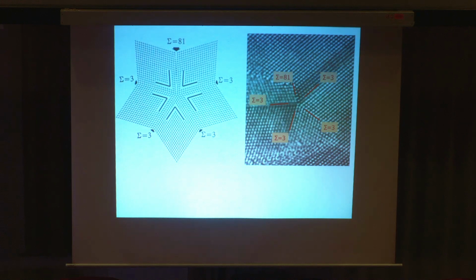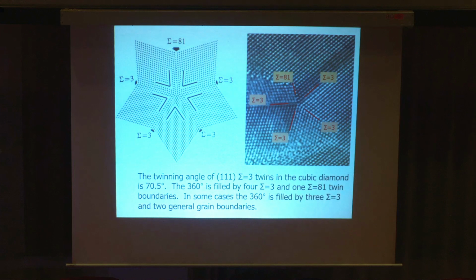If you take a diffraction pattern just from 1 twin, then you get a periodic diffraction pattern. If you take from the next one, you get exactly the same thing rotated 72 degrees. And another one, 144 degrees. And altogether you have all of them, 360 divided by 5. But if you take a diffraction from the center, all of them together, then you have 5 superimposed diffraction patterns, and it will have 5-fold rotational symmetry, of course. So this is what I thought it is, but it was not.